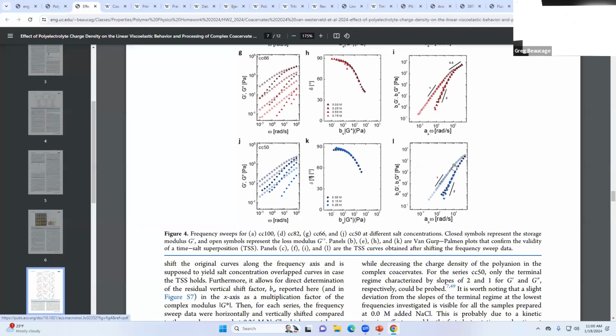You can see those different curves here combined, and he shifted them with this shift factor, right? That he calculated from these shift factor numbers. Oh, sorry about that. All right, so you can see he's got this line, that line, and that line. So there's 3 different measurements he did at 3 different temperatures, and then he shifted them with that shift factor thing.